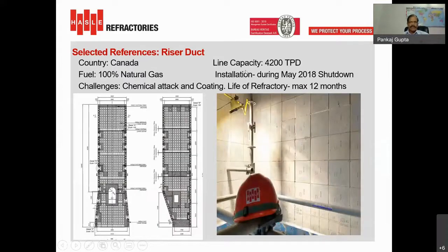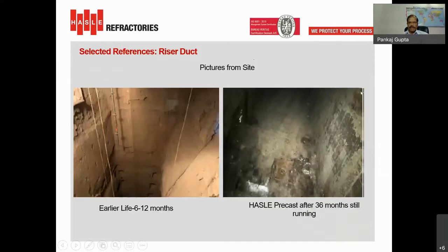This is a case for a 4,200 TPD plant from Canada. They are using 100% natural gas, but they are facing a lot of chemical attack and coating problems in the riser area, and they are getting a maximum of 12 months life. After 12 months, they are replacing the majority of the refractory in the riser area. We got the opportunity to install our modular lining during the May 2018 shutdown. This is the picture after 36 months, that is, after 3 years. There was only very small, minor repairing, but the condition is still very good, and we are expecting at least 1 or 2 years more life. So overall 5 years life will be achieved.